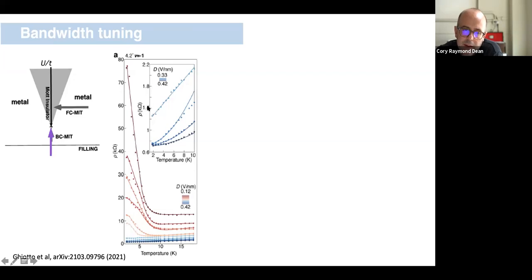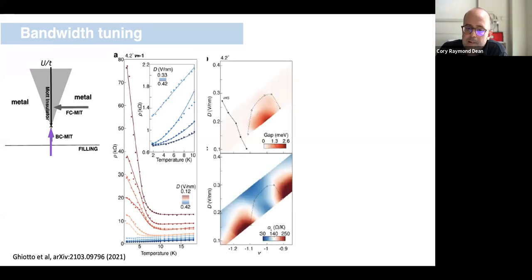And again, there's a regime of a critical displacement field where we see what appears to be very well described linear T behavior down to the lowest temperature of the fridge that we measured, about 1.6 Kelvin, which we identified as the quantum critical point in the system. So this tells us that we can reach the quantum critical point both by band tuning and by density tuning. I'm running a bit out of time, so I'll skim past this. Here we're correlating parameters that we measure through bandwidth and density tuning, but I'll move past that.